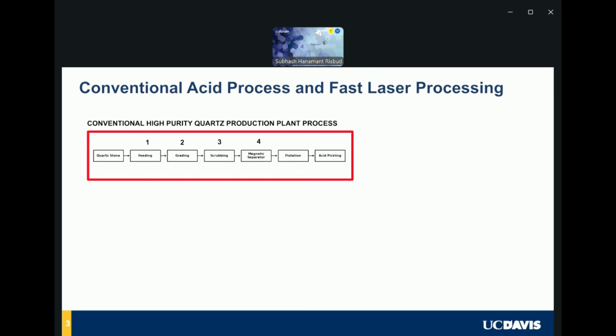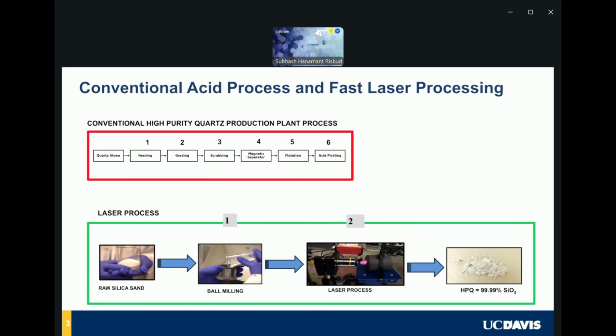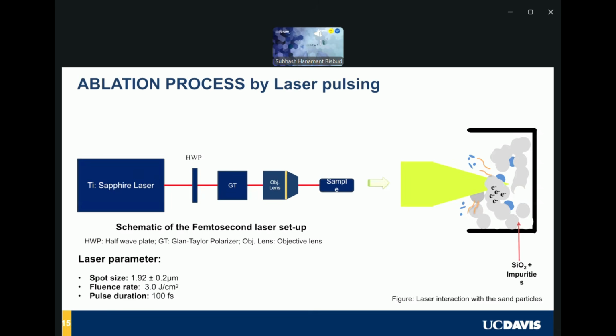And that was, normal steps, as you know, are the 1, 2, 3, 4 here that I'm showing, and acid pickling. But what we decided is let's try a different approach, which does not involve chemicals. So no acids, no water, no separation like that. We just take the sand, ball mill it, and then we go through the laser process, and we end up with getting pretty high purity silica sand, 99.9. And this is what we would like to use eventually for our work on melting it to fuse silica glass.